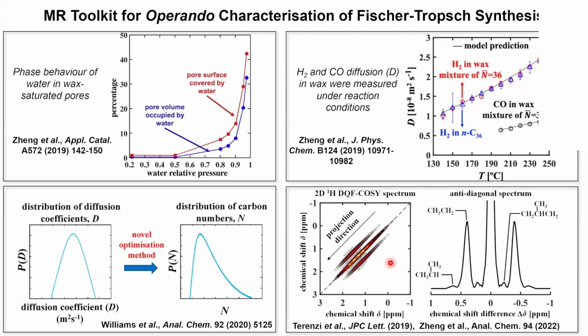Along the diagonal here, you see we've got these really broadened lines. This is, let's say, a couple of ppm of broadening. The interesting thing about COSY, or this type of spectroscopy, is that you're looking at J coupling, an intramolecular effect, which means the broadening caused by local heterogeneities in your field, caused by all the susceptibility differences, is not observed by a single molecule. Different moieties on the same molecule will be experiencing the same local field. And so that coupling is not broadened, and perpendicular to this diagonal, you still retain your spectral resolution.